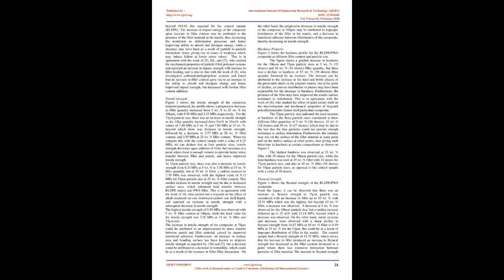Figure 4 shows the flexural strength of the RLDPE/PWS composite. From the figure, it can be observed that there was an increase in flexural strength at 75 µm particle size considered with an increase in filler up to 10 weight% with 25.51 MPa, which was the highest, but beyond 10 weight% filler, a decrease was observed.